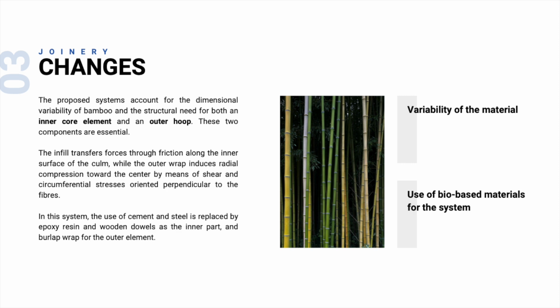And instead of cement and steel, I used wooden dowels of softwood pine, glued into the bamboo cane with epoxy resin, and an external wrap made of burlap fibers. This combination was chosen to keep the joint lightweight, simpler to produce, and less impactful in terms of embodied carbon.